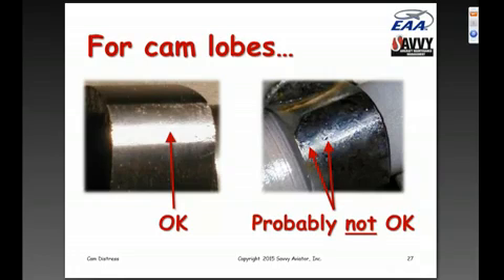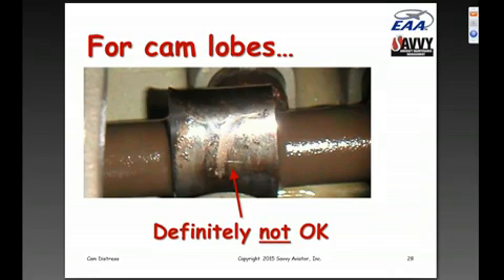So again, here are two cam lobes. The one on the left has some very tiny corrosion pits, but probably not enough to catch the tip of a sharp pick, probably not enough to have penetrated the carburized layer. The one on the right, you can see at least two deeper indentations there that almost certainly would catch the tip of a sharp pick and almost certainly have penetrated that 15/1000 inch thick hardened layer. And so that cam would be considered unairworthy and would need to be replaced. Here's a cam lobe that's in really awful shape with a great deal of material lost, and of course this one is a no-brainer. That engine has to be torn down before further flight.